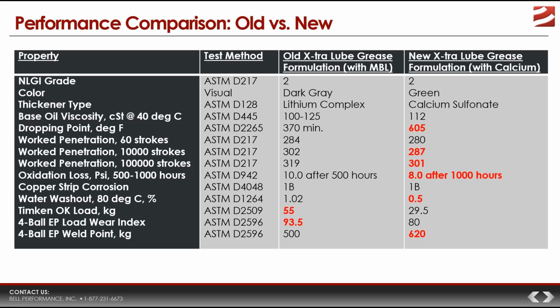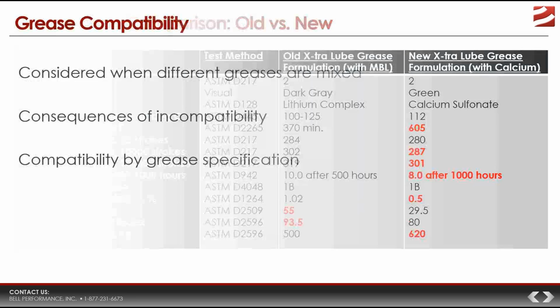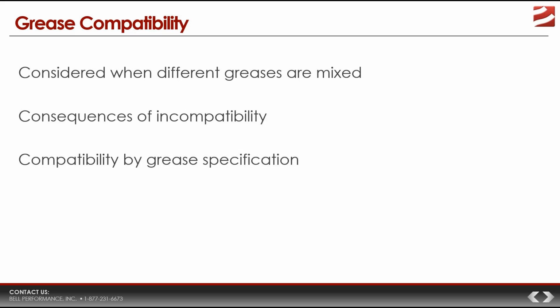So we have seen a performance comparison of the old and the new grease formulations in pretty much 6 key areas. And if we're looking at all of this evidence, we are really forced to conclude that the new X-tra Lube Grease outperforms the previous one in almost every key area, except for one Timken test and one load wear index test. So all in all, you would be forced to conclude that the new X-tra Lube Grease is significantly better in a number of really important ways over the old grease. So it's a better grease that we're transitioning to.